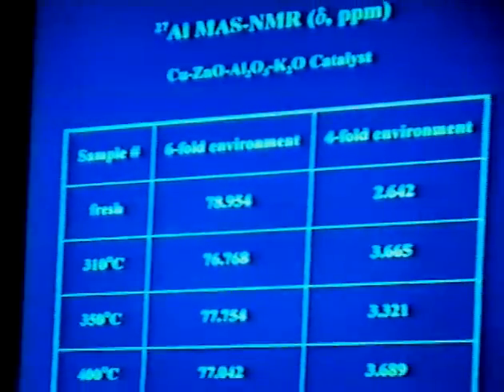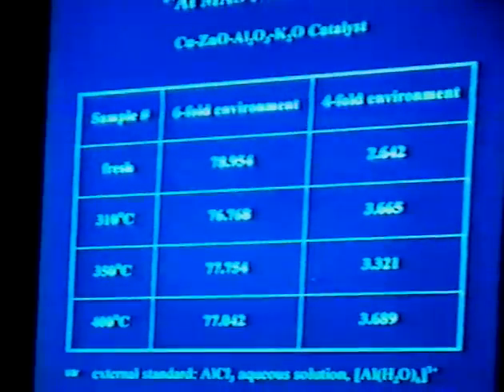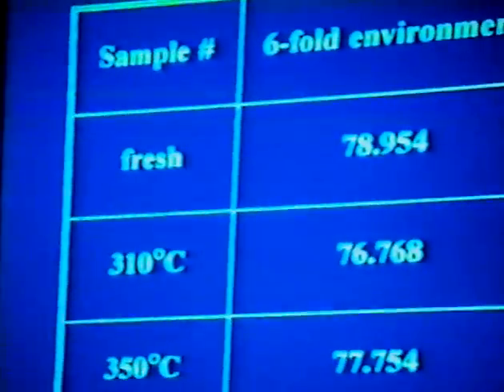Next one. This is the fresh catalyst. You can see on this page, here is 6-fold, and this is 4-fold. The catalyst taken out from the reaction always has a different chemical shift value from that of the fresh catalyst. However, the data shown here probably do not suggest whether the aluminum really changes or not. And the second thing is we cannot distinguish which one is coming from the surface contribution, even though the catalyst has been finely divided.